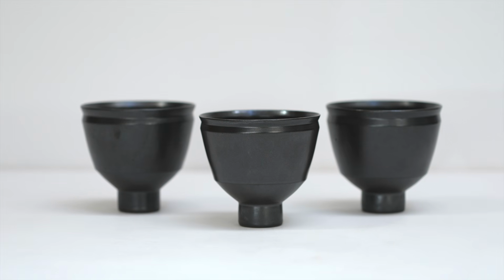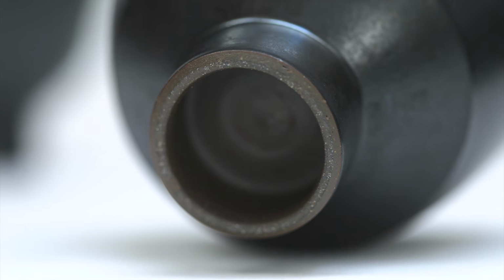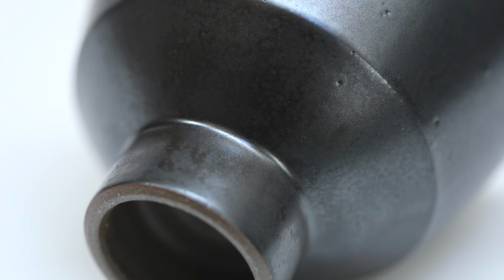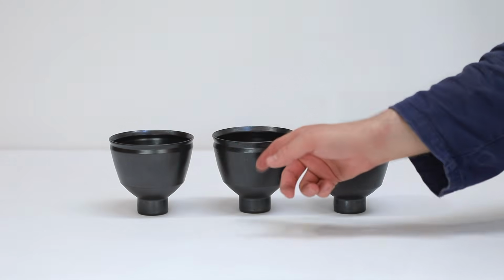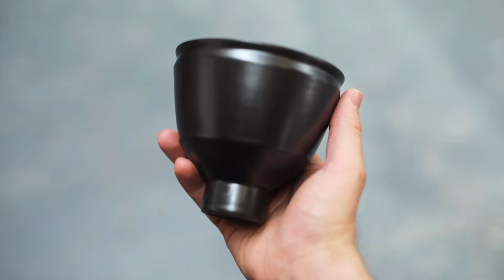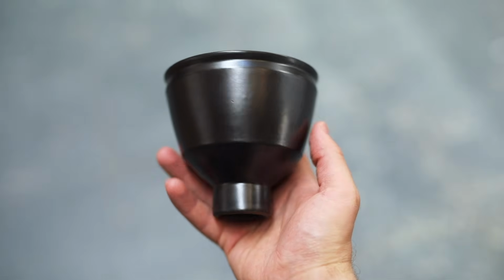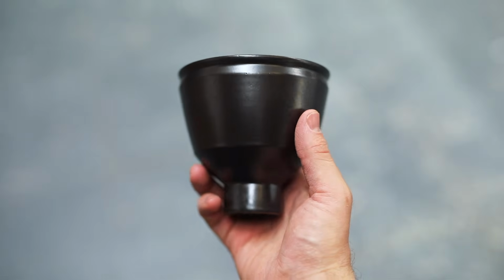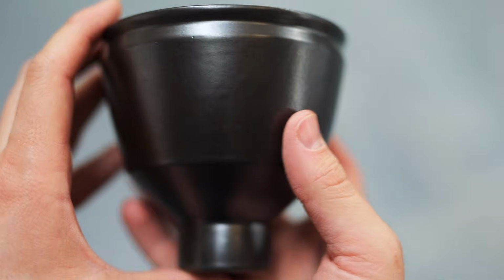I know I'm perhaps being a bit picky here, as ultimately these pots are quite nice. They just miss a lot of the markers I was aiming for, and there's a subtle patchiness across the entire piece in certain places, where the glaze was thicker, and I scraped it back down. They're about 50% of the way there, which I know might not seem very much, but really the easy thing about making these is achieving the shape. It's the surfaces and the clay that's a much harder thing to get right, as it requires far more testing.